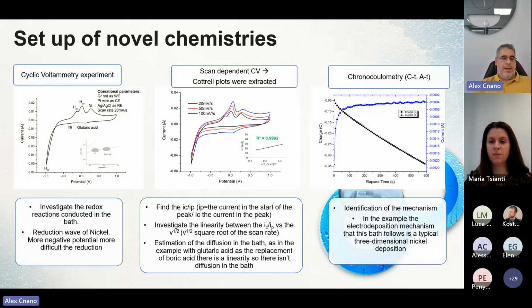For example, from cyclic voltammetry we can see the potential of the reduction of nickel, whether it is easy to do or not. From scan-dependent CV we can see the estimation of the diffusion in the bath, and of course from chronocoulometry we can extract some information about the mechanism of the electrodeposition, whether it is mass transfer or charge transfer, etc.